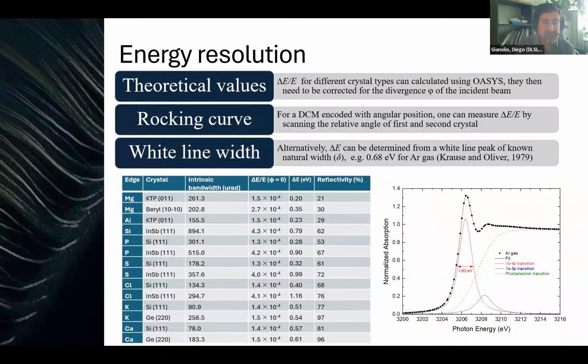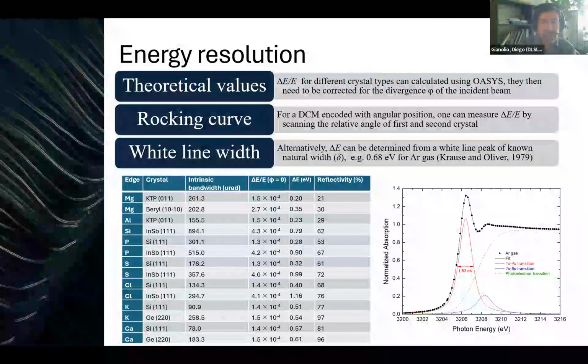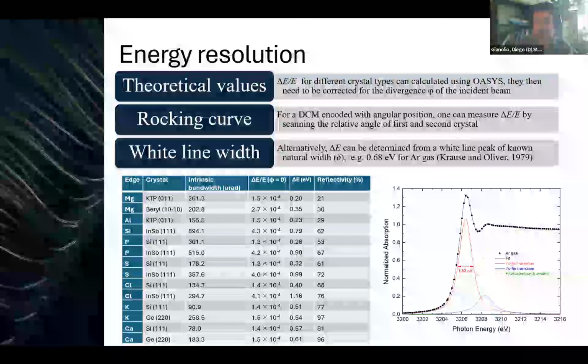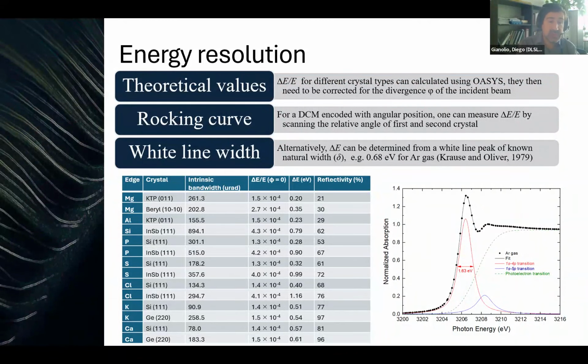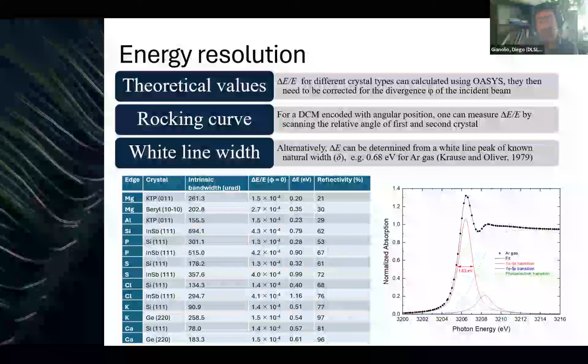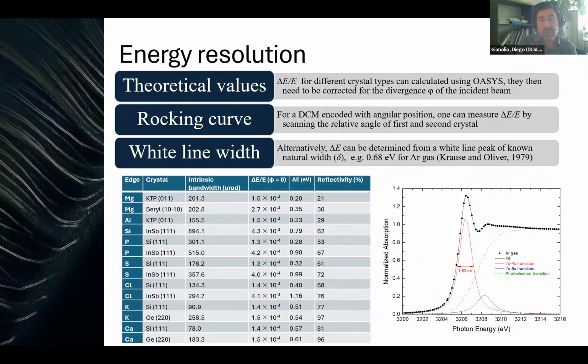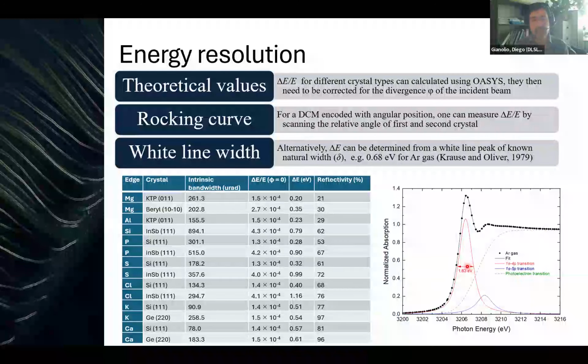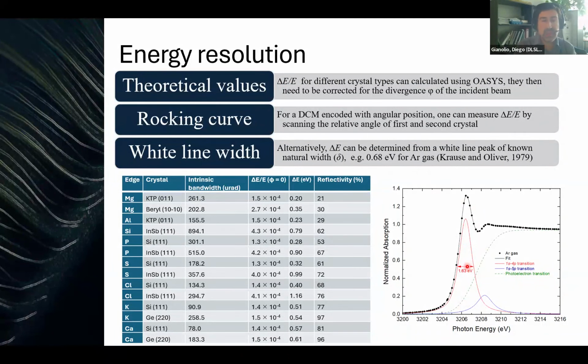One way is to rely on the intrinsic bandwidth of the crystal that has been used for the monochromator, and then eventually correct it for a residual divergence of the incident beam on the monochromator. For beamlines that have the possibility of reading the angular position of the monochromator with an encoder, one can actually measure it by doing a rocking curve, scanning the relative angle of the second crystal with respect to the first. And if this is not possible, there are other ways to determine the energy resolution by measuring the width of a white line peak. Here you see, for example, the peak of argon gas, and by doing a peak fitting of the white line, one can determine the full width at half maximum and then derive the energy resolution of the beamline.